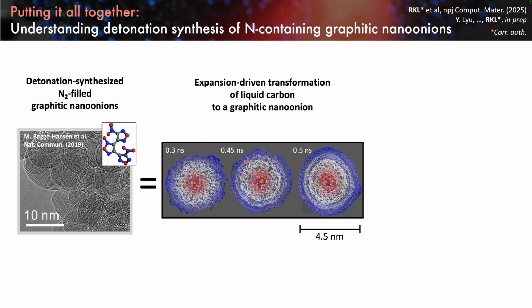So this is giving us a sense of how the particle solidifies, but what about nitrogen? What's happening with nitrogen and where is it in the particle? So what we did was prepare a number of simulations at different temperatures and pressures with a mixture of carbon and nitrogen, and we let those simulations run, asking: did the nitrogen and carbon remain miscible? Did they begin to phase separate? And if they do phase separate, what's happening?